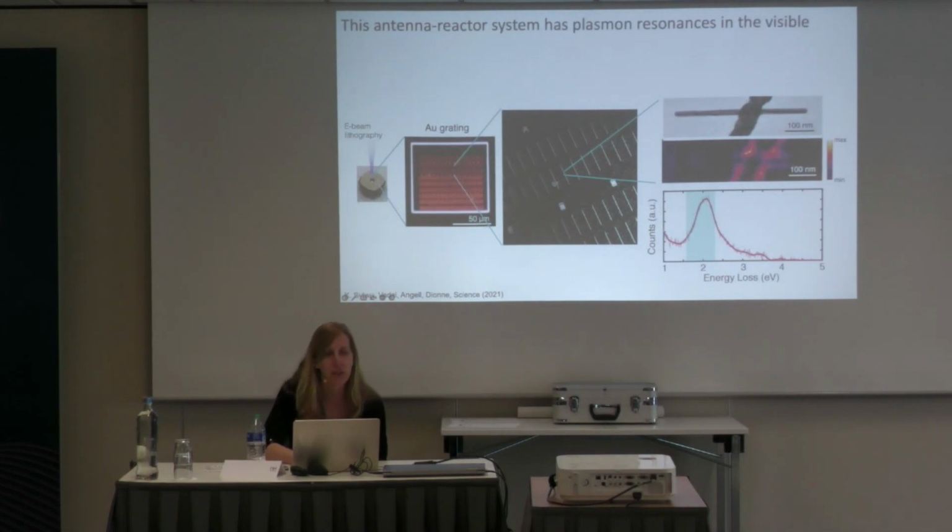So what we did is use electron beam lithography to pattern gold across the surface, and then we drop casted our palladium nanorods that were colloidally synthesized on top. Then we could map out the plasmon resonance, which is basically in the red, and you can see that visually in the electron microscopy image, right? Like the gold is looking this kind of vivid orangish reddish color.